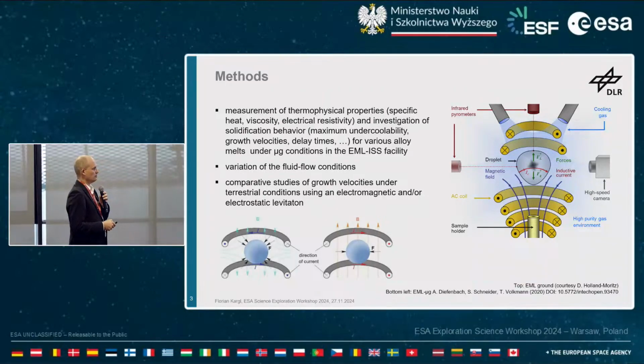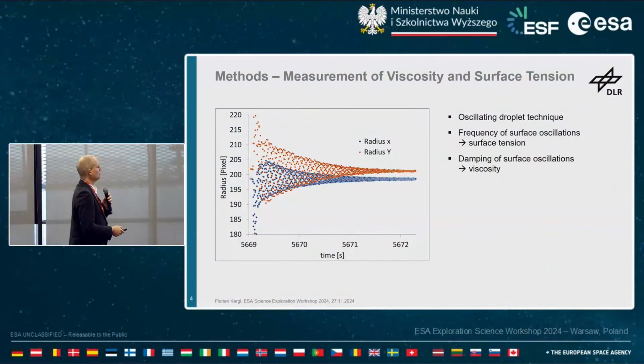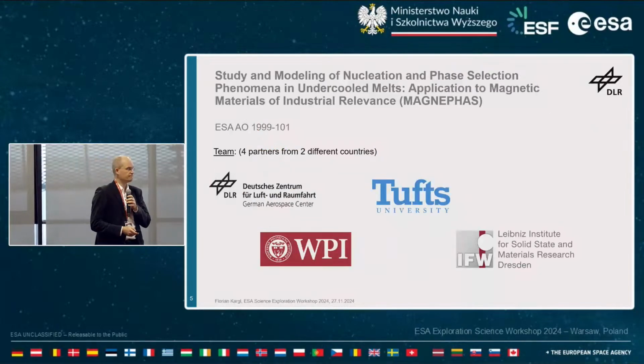Of course, the microgravity experiments are one part only. Of course, this is backed up by a strong ground-based program using electromagnetic levitation facility, but also for some samples, electrostatic levitation. I think that I can skip more or less. So this is what Fan has shown you. It's this oscillating drop method to determine, on the one hand, the frequency of the surface oscillations, deriving surface tension from that, and the other one was the damping of this oscillation in order to measure viscosity.